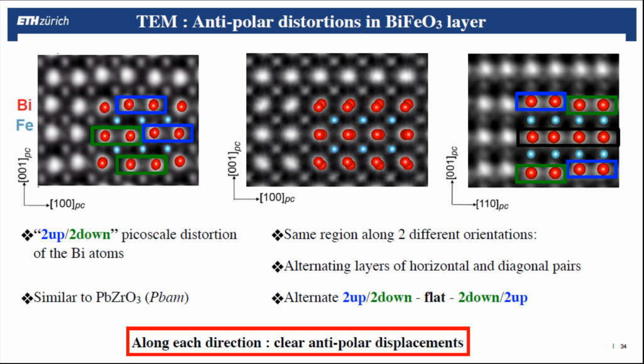They observed this type of structure, which consists in having here, in red, I colored the bismuth to help you, two that would move down and two that would move up, and continuing that way. And this is actually close to another material that is antiferroelectric, with this opposite direction of polarization. They also observed these two structures. So what you see here is actually the same distortion, but just with a rotation. So here we are seeing the 100 axis is here, and here we have the 110. So basically a 45 degrees rotation to visualize.